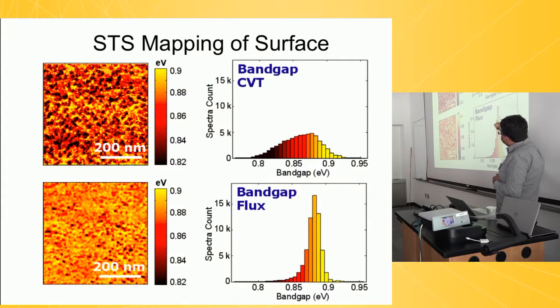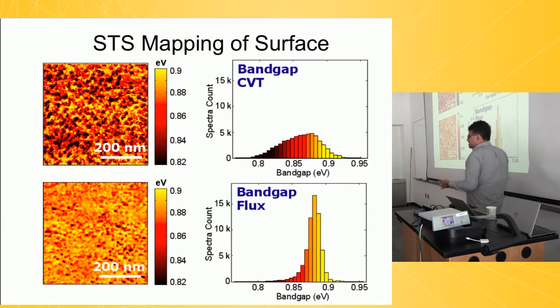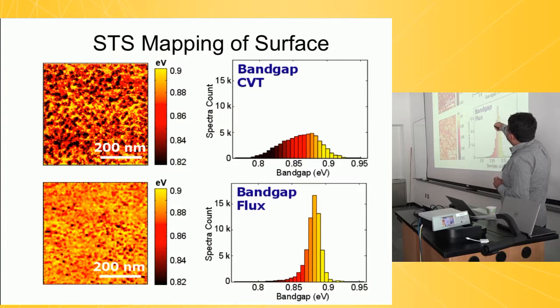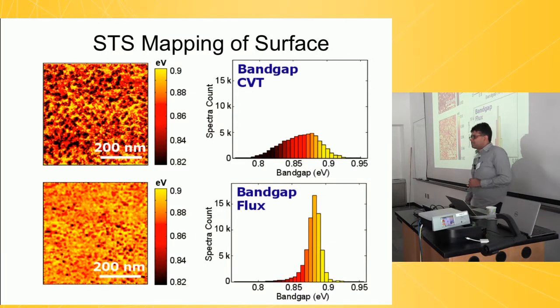If you look at the contrast in this image and the contrast in this image, you can see that this one has much less contrast, telling you that the gap in space is much more uniform. You can also just take a histogram of these gap values. Here is a histogram for the CVT sample. Here is a histogram for the flux sample. Once again, you see that the histogram for the flux sample is just much tighter than the histogram for the CVT sample. The average value of the gap is, of course, just about the same.